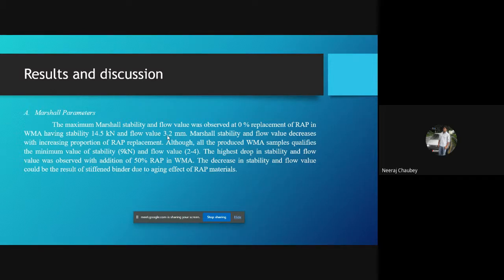The Marshall stability and flow value decreases with increasing proportion of RAP. Although all the mixtures produced with warm mix asphalt technology fall within the minimum requirement, that is 9 kilonewtons for Marshall stability and 2 to 4 for flow value.